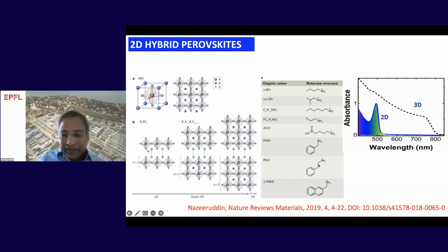And this cation, when you form a lead iodide, forms a two-dimensional perovskite. The two-dimensional perovskite shows a very nice absorption, but it absorbs only up to 500 nanometers. On the contrary, three-dimensional perovskite absorbs the whole visible region up to 800 nanometers. But the beauty here is that two-dimensional perovskites are extremely stable compared to three-dimensional perovskite. Can we combine the two-dimensional perovskite, which is extremely stable, with the three-dimensional perovskite, which absorbs all the visible light but is less stable? By optimizing these two together, we can have both stability and high efficiency of the